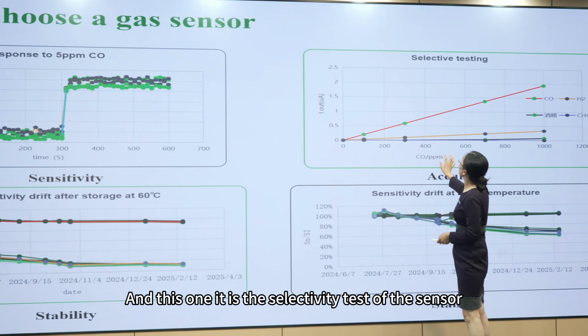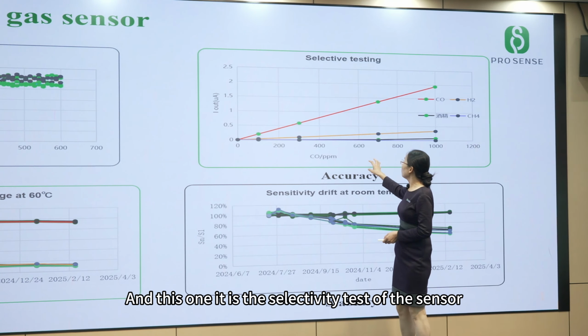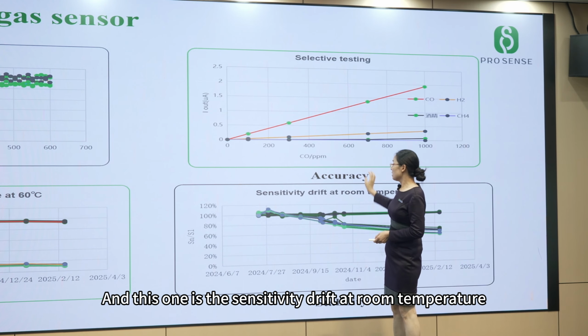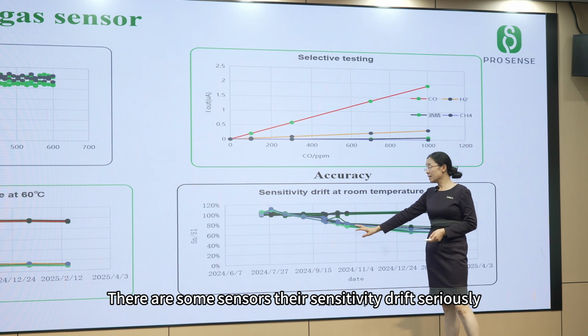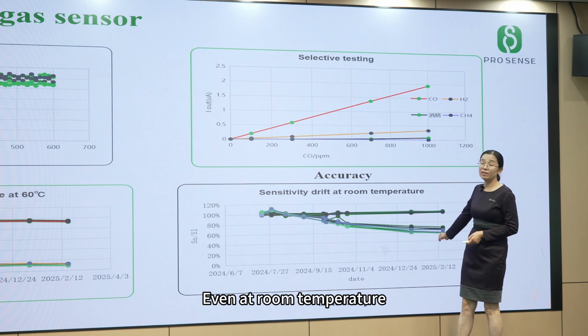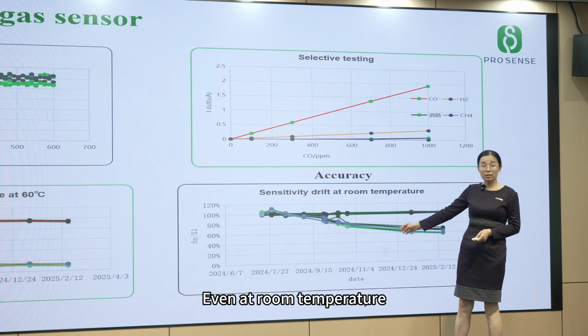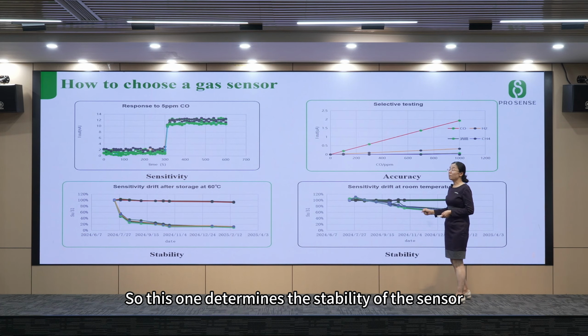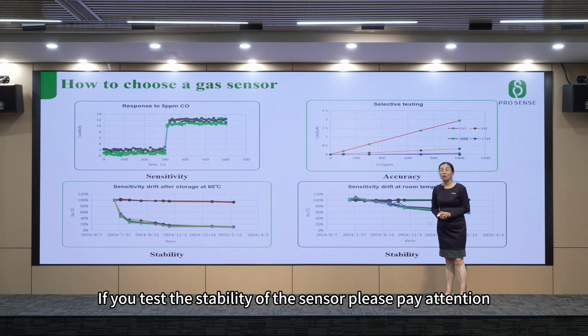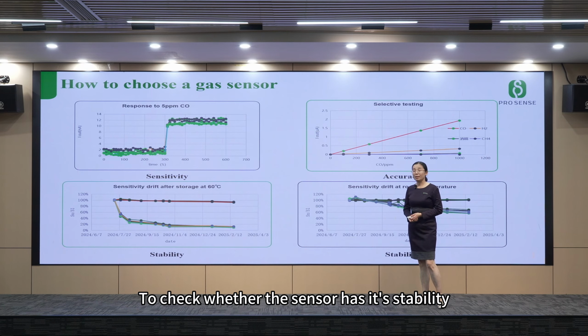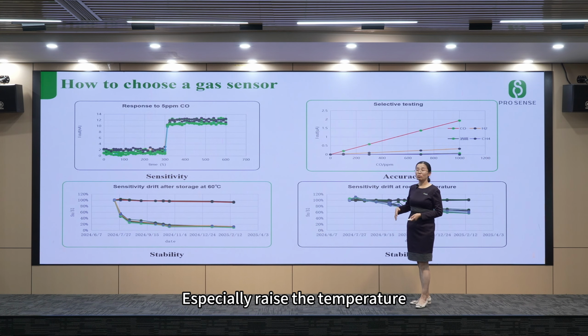And this one is the selectivity test of the sensor. And this one is the sensitivity drift at room temperature. There are some sensors whose sensitivity drifts seriously even at room temperature. So this one determines the stability of the sensor. If you test the stability of the sensor, please pay attention. Prolong your test period to at least 3 months to check whether the sensor is stable, especially at raised temperature.